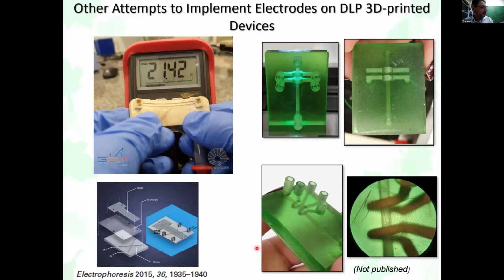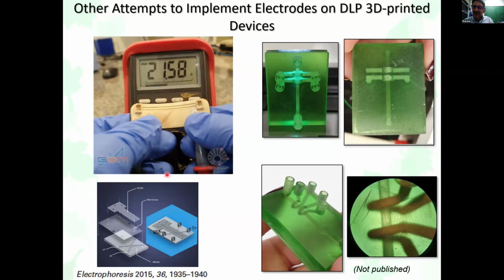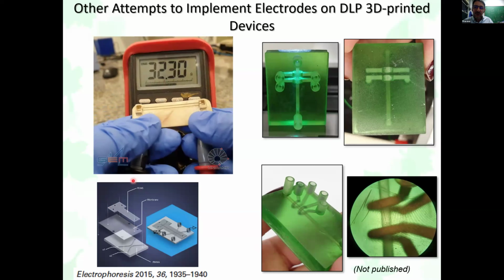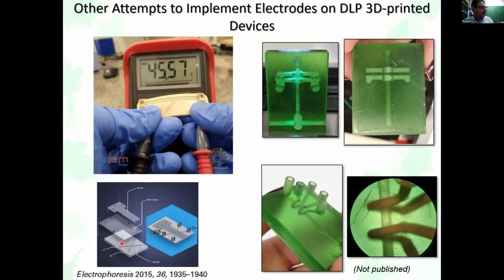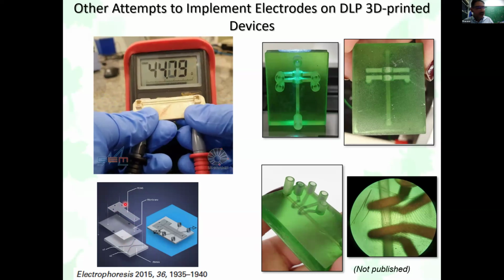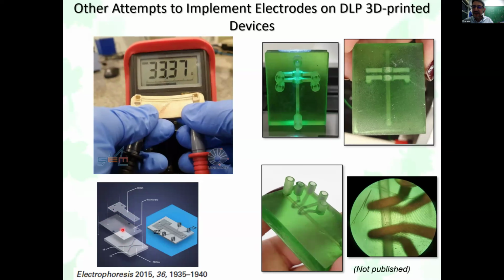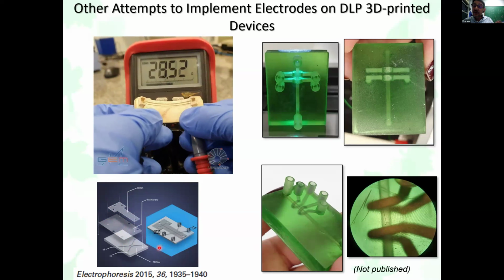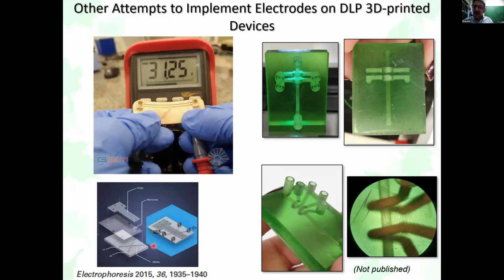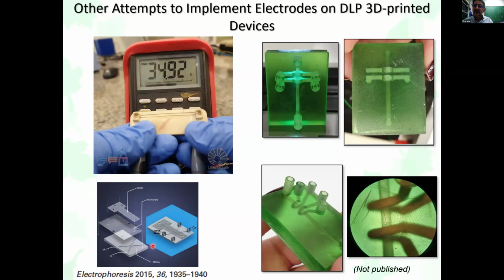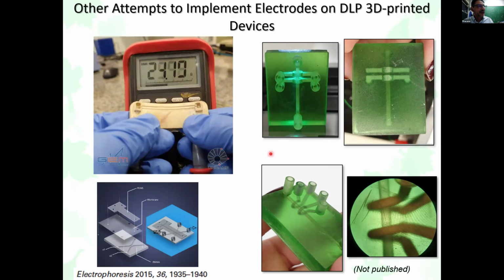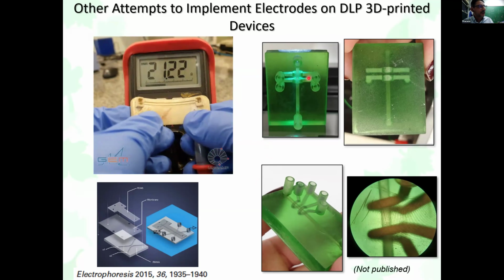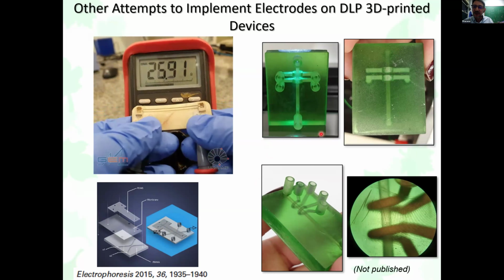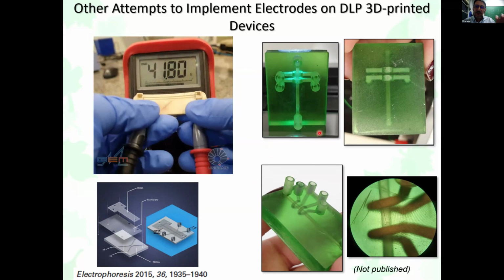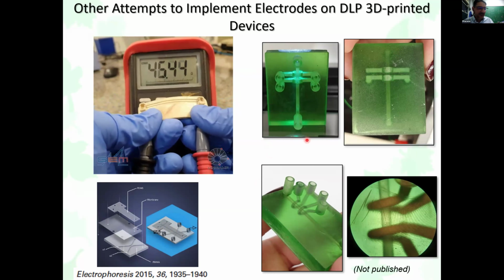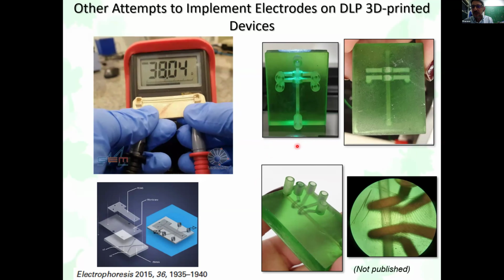And also, we demonstrated in 2015, this is an example of a hybrid device also. This is a PDMS device over a polyester layer where we can actually use electrolyte solutions as electrodes. So we can even use electrolyte solutions, filling these channels with electrolyte solution, and you get these electrodes coupled to the separation channel. This is really interesting. It's really cheap also.